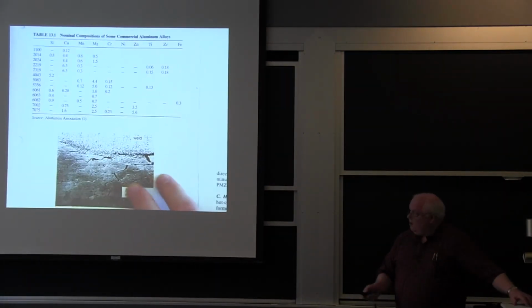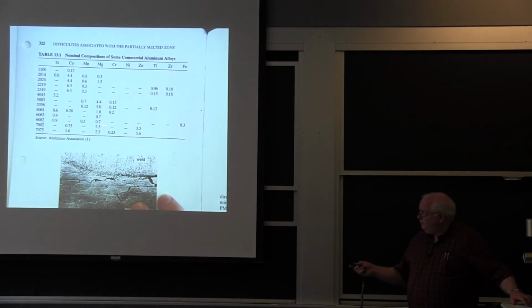The other problem with the heat treatable alloys is if you're welding them in their full strength condition, you can't get 100% joint efficiency. You may only get 60% joint efficiency. So yeah, you can get 40 KSI in 6061 aluminum as opposed to 25 KSI in 5083. But after you weld it, you're down to 25 KSI in the weld, because the weld metal is a non-heat treatable, non-precipitation hardened alloy. So you're not going to do any better in the weld metal than you do with non-heat treatable alloys. So that's a problem.